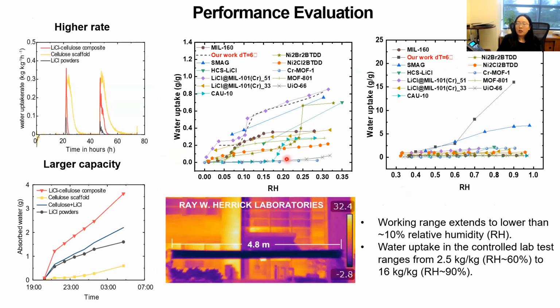So we were looking at the kinetics as well as the capacity of this new composite material, the cellulose-salt composite material, and we observed both a higher rate of water absorption as well as a larger capacity of the composite compared with just these two added together. So this shows some synergistic interaction between the cellulose material and the salt and the salt solution.